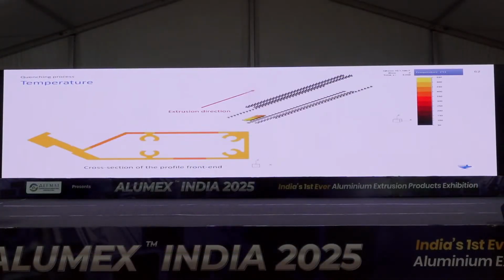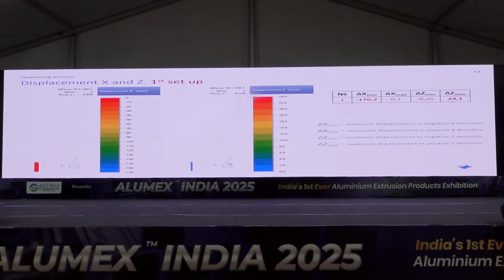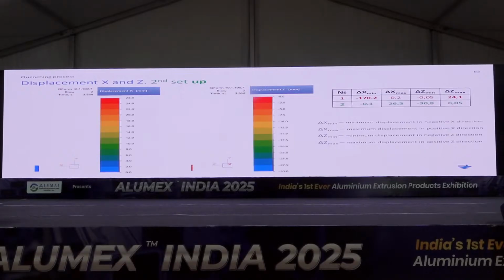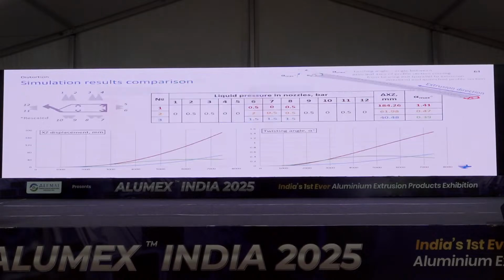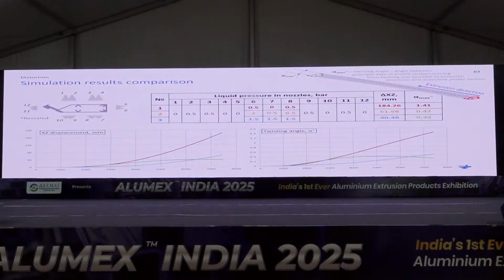And then, if it is not good, you start to do some optimization. You increase or reduce some pressure in some nozzles and get a result. And finally, you can check and compare different setups considering the overall X and Z displacement. And you can create some graphs for the characterization of the deformation, like the twisting angle of the profile, which, as you can see, was optimized and became much lower compared with the first red curve.